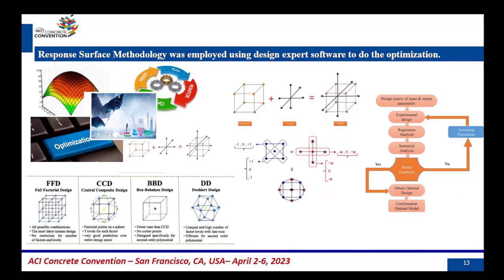So considering this problem, when we tried these materials individually in the 3D printed mix, although some of the properties were improved, on the other hand we had to compromise some of the parameters. So to eliminate that problem, we decided to use these modifiers in different combinations. But how do we know that this mix will be the optimized combination? To do that manually, there would be a lot of experimental effort. So to eliminate that effort, we use a design of experiment technique, response surface methodology, and in response surface methodology, we use central composite design to reduce that experimental effort.